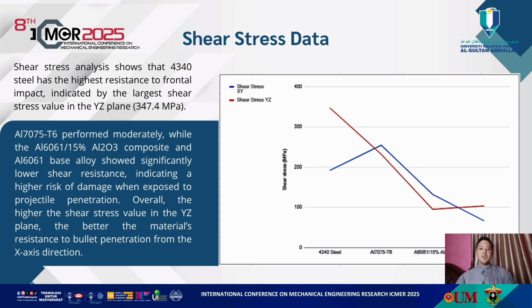Shear stress analysis shows that 4340 steel has the highest resistance to frontal impact, indicated by the largest shear stress value in the YZ plane at 347.4 megapascal. Next, the aluminum 7075 T6 performed moderately, while the 6061 with 15% aluminum oxide and base alloy showed significantly lower shear resistance, indicating a higher risk of damage when exposed to projectile penetration. Overall, the higher the shear stress value in the YZ plane, the better the material's resistance to bullet penetration from the x-axis direction.